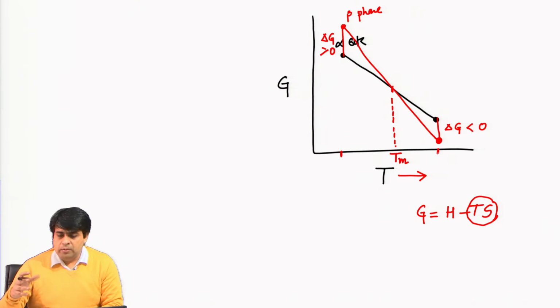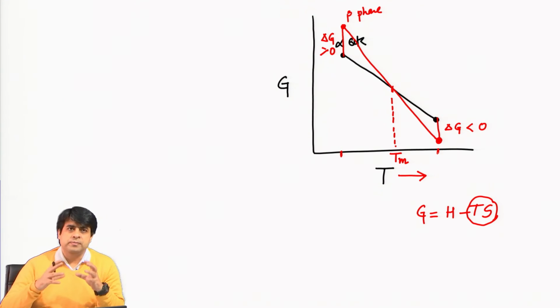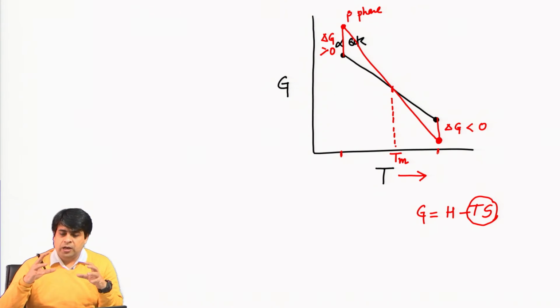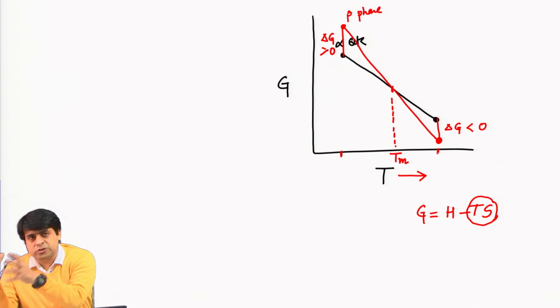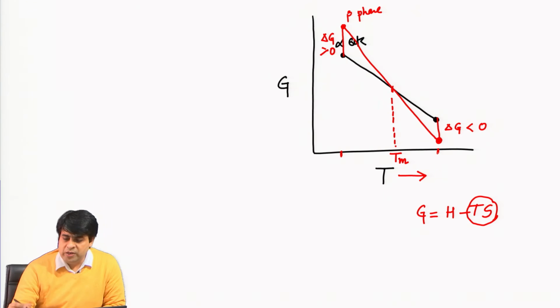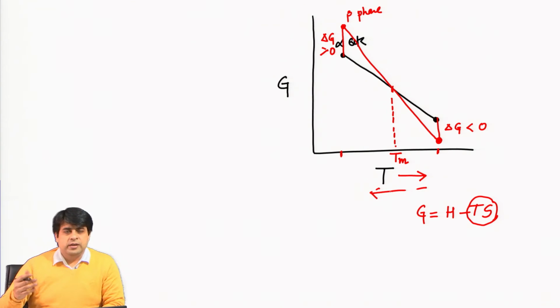Because of that this beta phase is stable. But in nature, both systems have a hexagonal structure, and when you supply heat to the system, alpha quartz immediately changes to beta quartz. When you decrease the temperature, energy is dissipated, and because beta quartz has a very small activation energy, this beta quartz immediately changes back to alpha quartz. When you have this kind of situation, your polymorphism is called a displacive polymorphism.